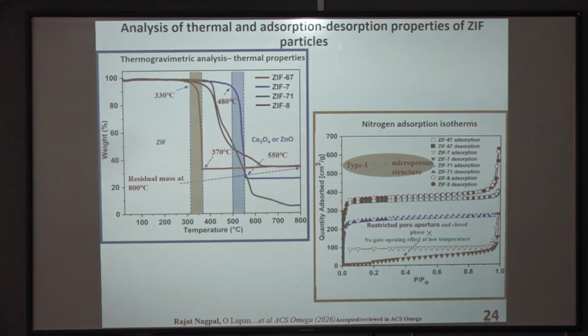And to get insights about the thermal stability, here we can see specifically for ZIF7 and ZIF67, quick thermal degradation can be observed compared to ZIF8 and ZIF71. And to get insights about the adsorption isotherms, here we can see for 3 ZIF particles, ZIF71, ZIF67 and ZIF8, quick nitrogen uptake and saturation, which is associated with the type 1 adsorption isotherm, micropore structure, but not for the case of ZIF7. Using nitrogen adsorption isotherm, even at high nitrogen pressures, there is no appreciable adsorption of nitrogen in case of ZIF7 because of its restricted pore aperture, and no gate opening effect was observed at low temperature.